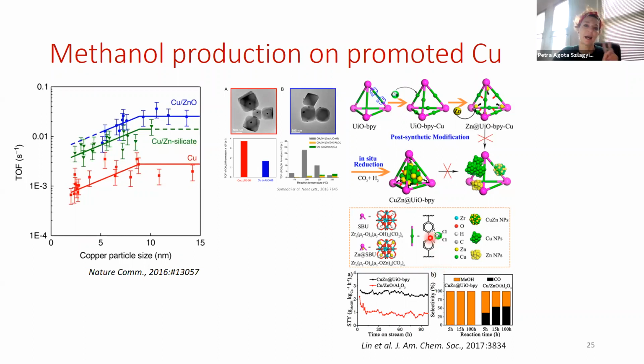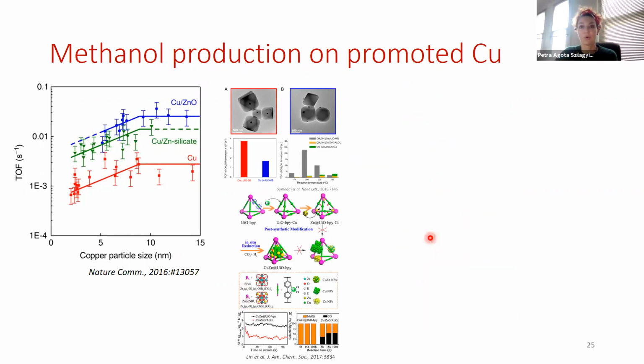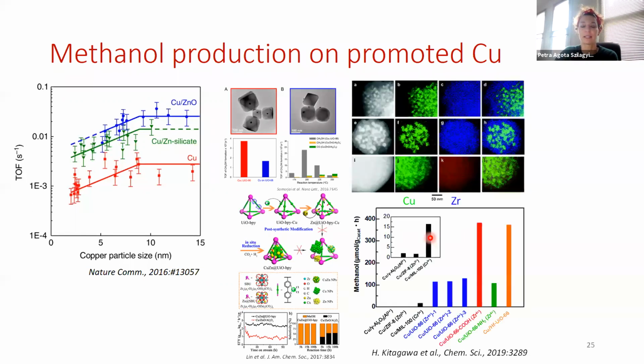However, there are two things that happened here. On the one hand, the copper was nanoconfined. On the other hand, it also interacted with the zinc. So we don't quite know which effect is more prevalent. More recently, there has also been a work in which smallish copper particles were distributed and dispersed within the MOF particles. So they were still essentially core-shell type particles. They're not sitting inside the pores, but the MOF framework is growing around a bunch of copper particles.